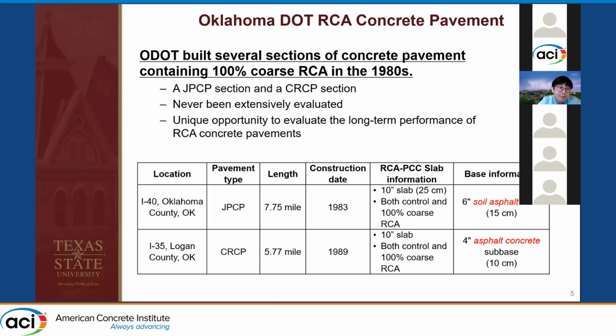In this table, as you can see, we have 2 sections. One section is the JPCP section. It is located on I-40 near Oklahoma City, and the length is about 7 to 7.5 miles. The original RCA concrete pavement was built in 1983. We had 10-inch slabs containing 100% coarse RCA, and we also have a control section on the same pavement. The base for I-40 is 6-inch soil asphalt. And we also have our CRCP section located on I-35. It is around 6 miles, and it was built in 1989. The slab thickness was also 10 inches.